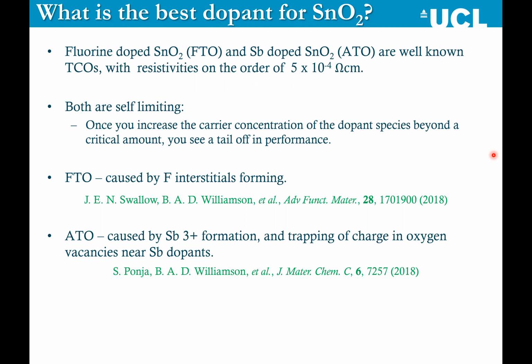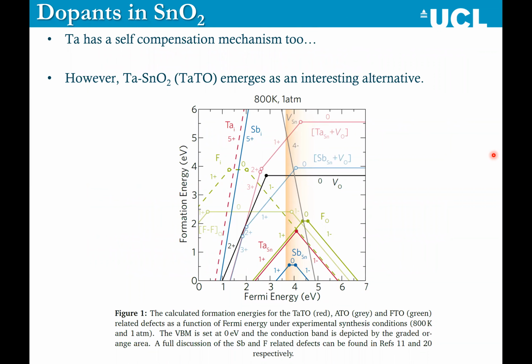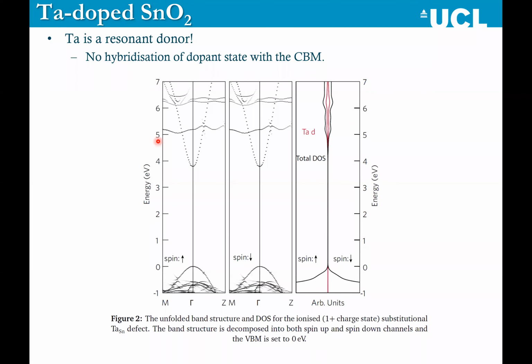So now that we kind of understood the limitations of tin dioxide, we could go on and find out where there are more optimal dopants. So we did a screening, and we used our chemical knowledge. If we want a dopant that's going to have 1 extra electron, it's not going to be on the oxygen site, it's going to be a transition metal dopant, then your options are vanadium, niobium, or tantalum, because they're all 5+. Vanadium didn't work because the vanadium excess electrons stayed on vanadium, reducing the vanadium atom, making a colored tin dioxide. Niobium just wasn't a good dopant, but tantalum actually emerged as the ultimate dopant. Very low energy dopant, so very easy to incorporate. And what the band structure analysis told us was that the donor D states would sit very high above the very dispersed conduction band minimum, meaning that you would have the same type of mechanism as we saw for IMO.